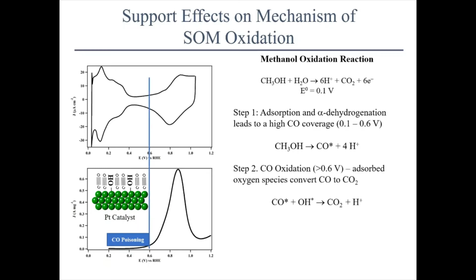Now, the effective oxidation of CO requires there to be some kind of oxygen species around, meaning there has to be some kind of adsorbed PtO or PtOH species that comes on. If you look at the CV in the oxide region, we start to put those oxide species on. So it's not surprising that we see the oxide onset happen at the same time that we see methanol oxidation onset to be the case. So everything before this line, where we don't have any oxide, is where we get CO poisoning and a suppressed methanol oxidation wave, meaning we don't really see methanol oxidation.